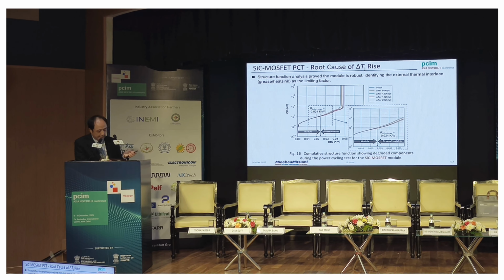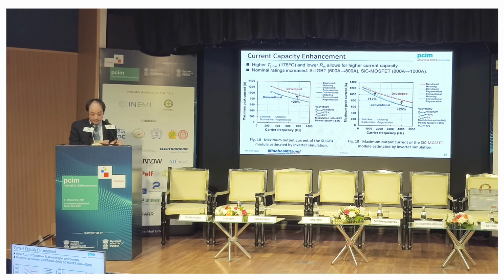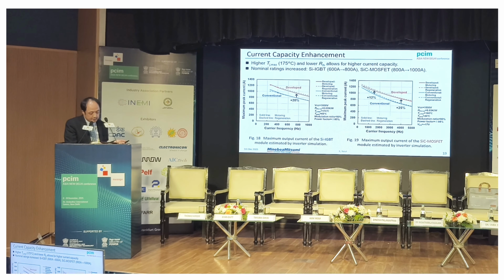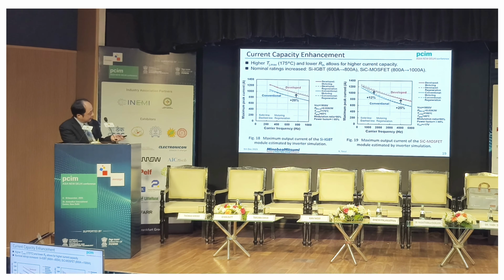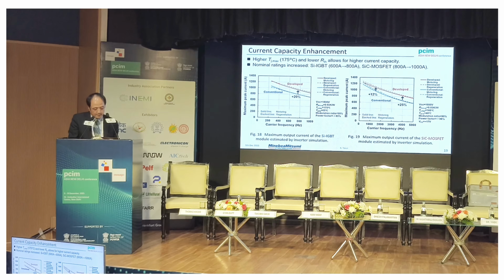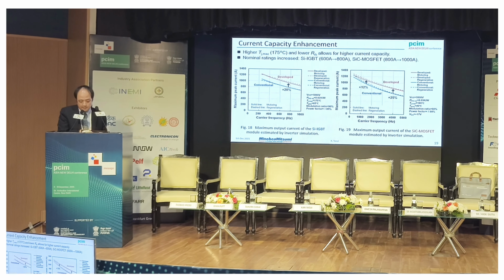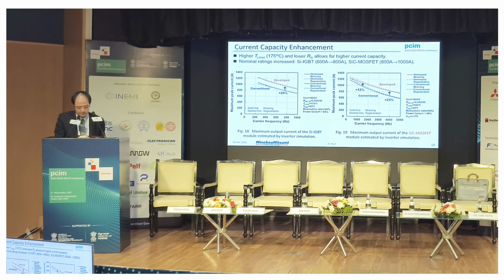And in the low frequency range, I mean the left side, the benefit of the maximum temperature increase was mitigated because of the steep and positive temperature dependence of the conduction loss of the SiC MOSFET. But in contrast, the switching loss is so low in the case of the silicon carbide MOSFET, so the frequency range is widened. The x-axis is different for the left-hand and right-hand side graphs. So the silicon carbide MOSFET can be used for much higher carrier frequency.